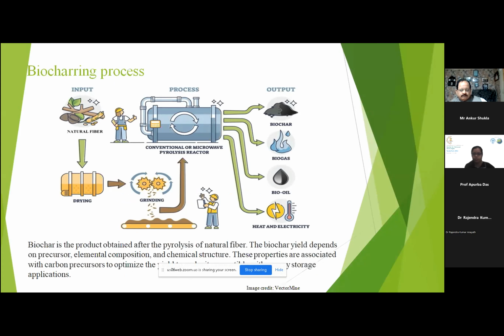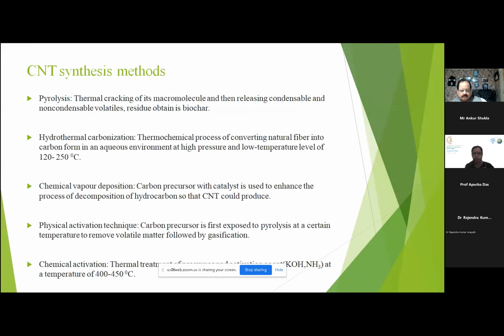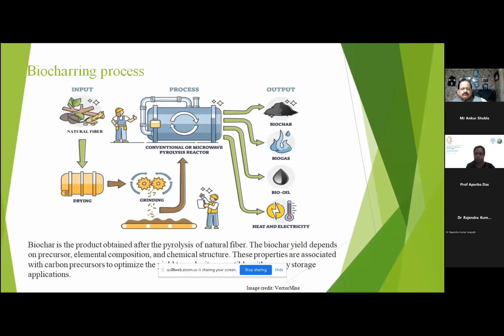That biochar yield determines the elemental composition and chemical structure. This will determine whether it is compatible, or has the high yield, to make a carbon-based energy storage application or not. So I have taken the pyrolysis synthesis method, in which biocharing is the most important process.